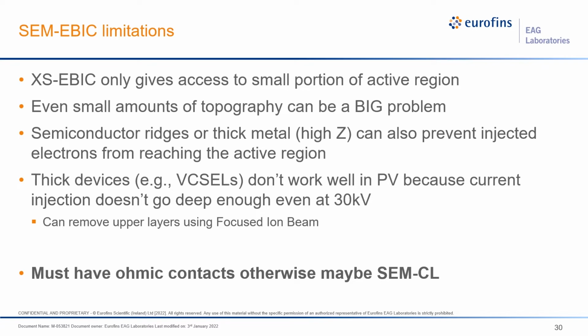Thick devices such as VCSELs and other devices don't often work that well in plan view, just because the current injection is limited by the kV. So you've got a couple of microns probably of depth that you can actively inject. And with VCSELs, you've often got many microns of mirror layers above the active layers. But we can use the focused ion beam in some cases to gain access.